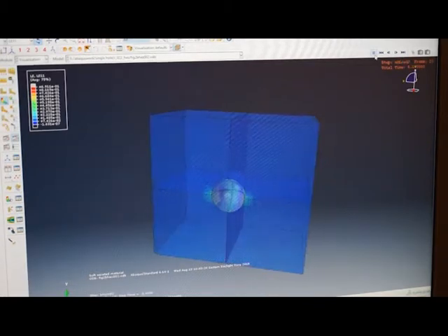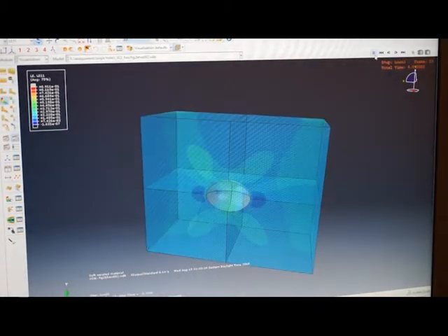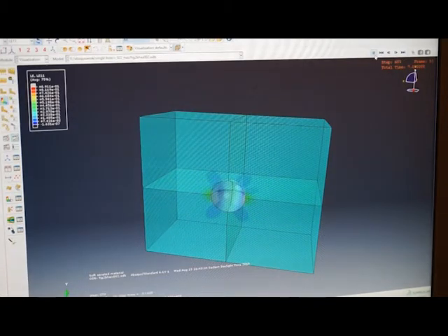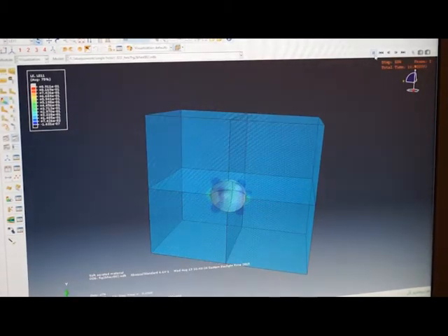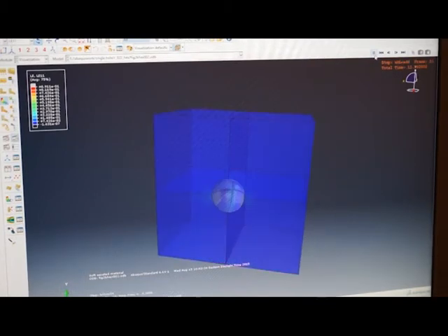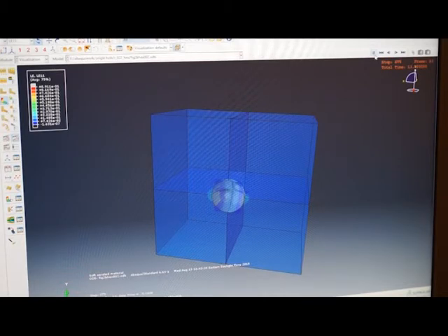Then, the surface tension is applied in the center hole, and due to the presence of the surface tension, the stretched hole will shrink back a little. One can see in each step the hole will deform less, since the surface tension is manually increased in each step. And this fully illustrates how the surface tension will influence the deformation of this composite material and further increases material stiffness.